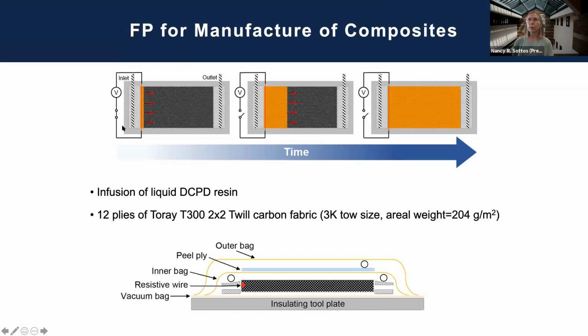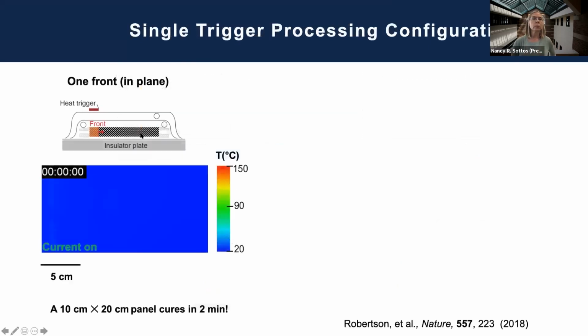The location of the trigger will vary, but we started out with the trigger on one side of the composite and let the front propagate smoothly across the panel. So that's what I'll show first. So we start out with this single trigger processing configuration. And so there's a heat trigger, and then the resistive current is just turned on for a short while, and then the front propagates across the panel. And what I'm going to show you below in the video is an IR image where the IR camera is looking down on the panel. And this is a fairly good sized panel, a 10 by 20 centimeter panel. And you can see the current is on. That's just how we initiate it. The front starts moving across the panel, and we get this stable propagation as the exothermic reaction occurs.